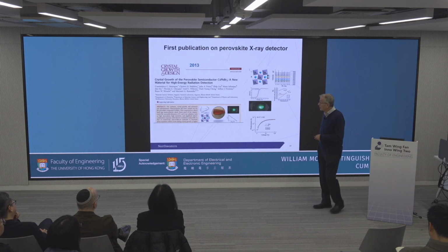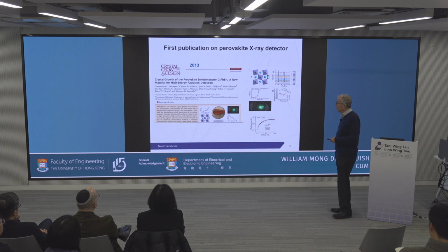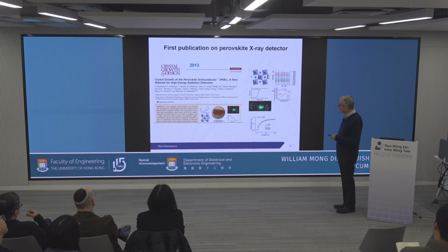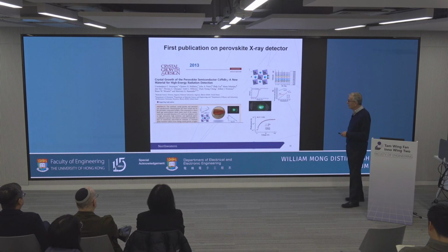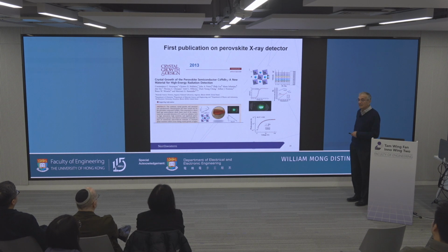What the iodides, the lead perovskites, tin perovskites did to the PV field, the bromides actually impacted another field: X-ray detection and gamma ray detection. And this, again, we published in 2013. For the first time, we claim that the cesium-lead bromide perovskite, bigger band gap, red material, can actually detect X-rays and gamma rays.